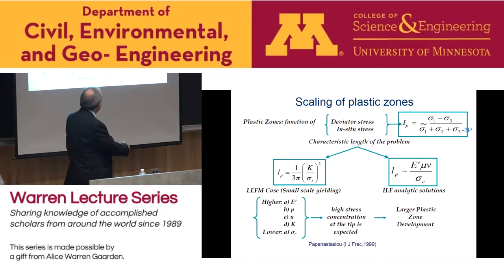And we try to do some scaling, looking into some characteristic length. And apparently, we expect that this characteristic length, which defines the size of plasticity, should be proportional to the deviator of the in situ stresses. It will depend also on the rock parameters like toughness and tensile strength.